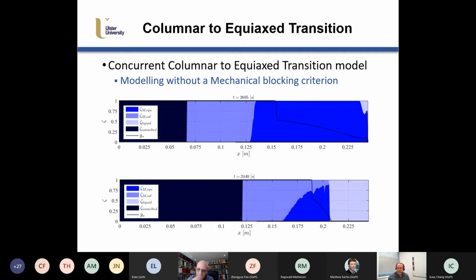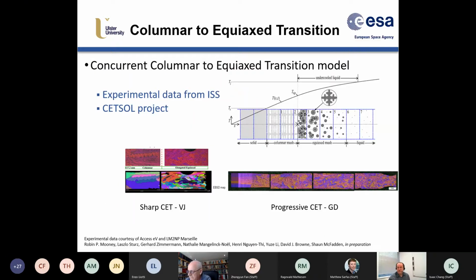And you see the solid fraction in the black line. But then in the case beneath, you see a very progressive transition from the equiaxed as it overtakes the columnar solidification. So this is the behavior, qualitatively, that we were looking for in the modeling.